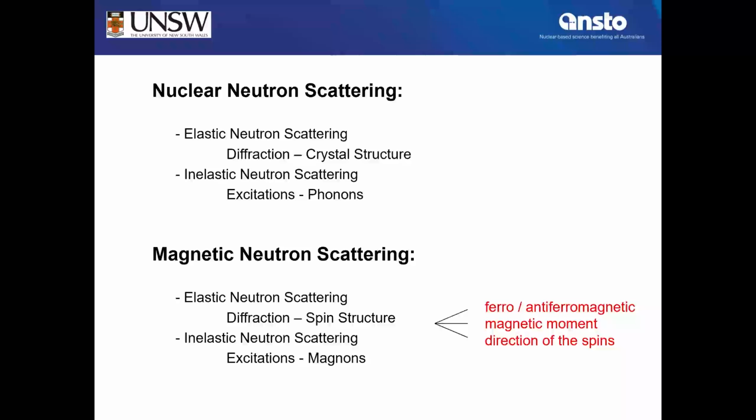So magnetic neutron scattering is pretty unique. Just think of an antiferromagnet, one spin up, one spin down, and so on. From outside, it does not look magnetic at all. And if you place it in a magnetic field, there is no force acting on it. So how can we prove that this is an antiferromagnet? This is indeed neutron scattering, the best, if not only technique to do that with great accuracy. On top, inelastic neutron scattering, excitations, magnons.